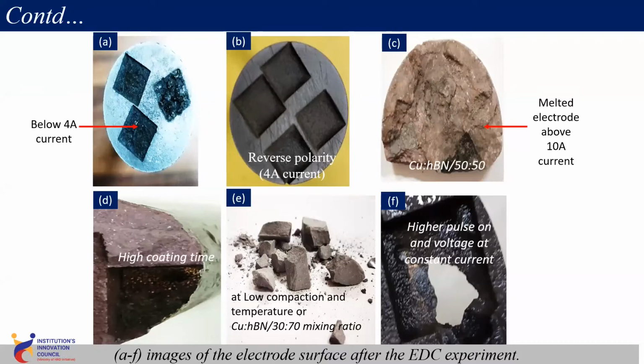So the electrode surface after experiment, we have decided the trial. I have told you that we have performed the trial experiment. Below 4 ampere current, it is observed that there is no deposition. It means tool material doesn't get melted and doesn't get deposited on the workpiece surface. So below 4 ampere, we have not performed the experiment. Then we have gone forward above 4 ampere.